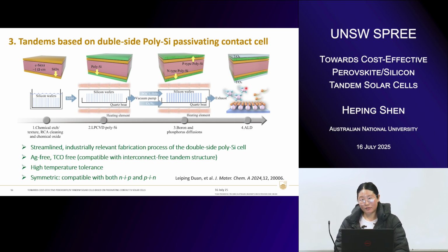On top of each we have a barrier layer, titanium. Of course, depending on how we use these cell structures, we will deposit the electrode on top of it. We were able to achieve these cell structures using not only industry-relevant processes, the LPCVD method or PECVD method that is widely used for the TOPCon cell structure, but also a streamlined process where we can finish the cell structure in a very short time, like half a day. Very nice cell structure and fabrication flow.